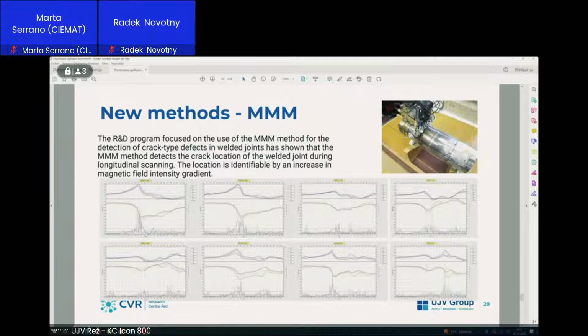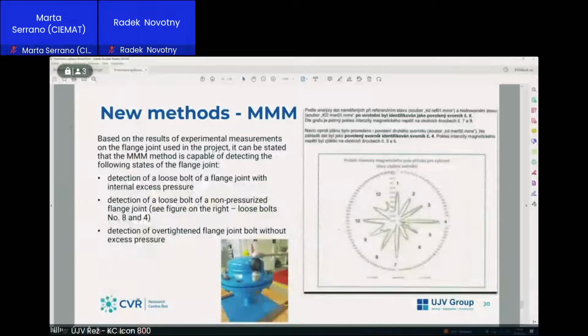Here I put an example from testing of a dissimilar metal weld with a crack in this area found via this MMM method. And we had, in this case, 8 traces. On traces number 1 and 8, you can see there is a peak of gradient of intensity of magnetic field. So this was in the area between traces 1 and 8. In this way, we evaluated that this method can be used for detection of cracks.